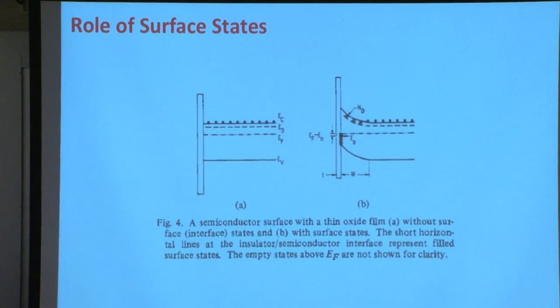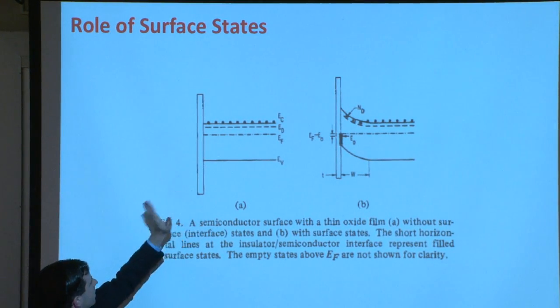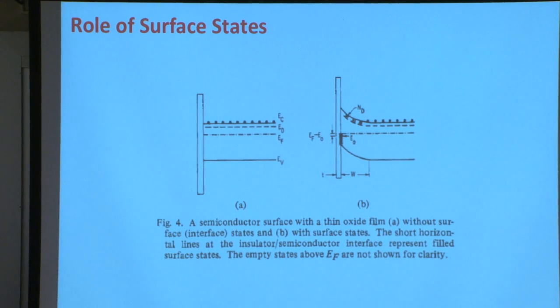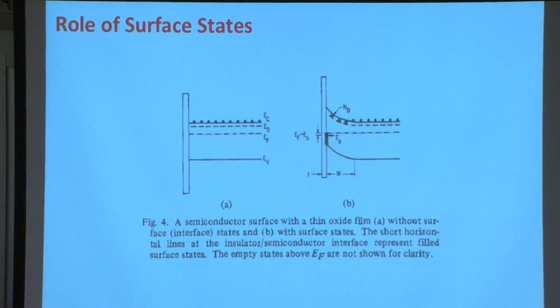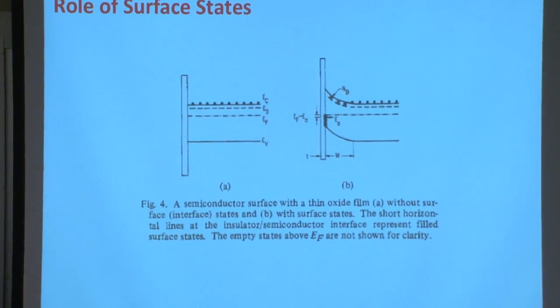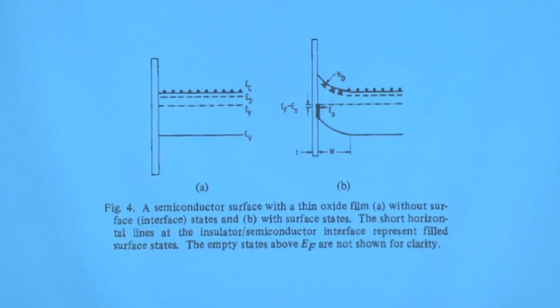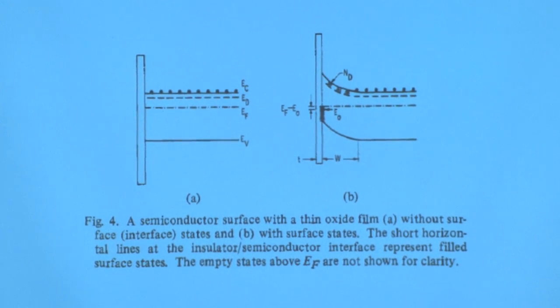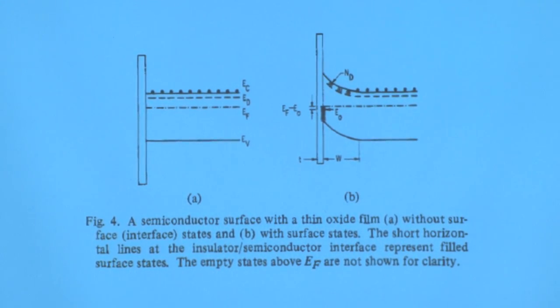It's maybe a few nanometers typically in a semiconductor. And it's very large in bandgap because we formed a metal oxide, or a semiconductor oxide, let's say a silicon oxide, a silica layer at that surface. So if we have pure silicon, we expose it to air, the silicon will react with air and form a very thin SiO2 layer, or silicon oxide layer. And that's what this represents. It's a very large bandgap material, and it's very thin.